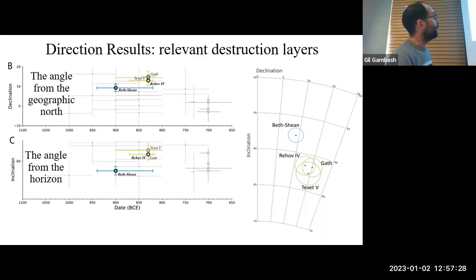Here we're not talking only about Beit She'an or Rehov 4, but we have two other sites. We have Gath, Tel Safi, the famous destruction that is also historically dated. So we have just a perfect match between Rehov 4 and Tel Safi Gath, which were both claimed to be destroyed by Hazael. You get exactly the same direction, and also Tevet 5, Horvat Tevet, we have exactly the same direction. You see also inclination and also declination, just a perfect match of these three sites that were presumably destroyed by Hazael. And Beit She'an is somewhat different.